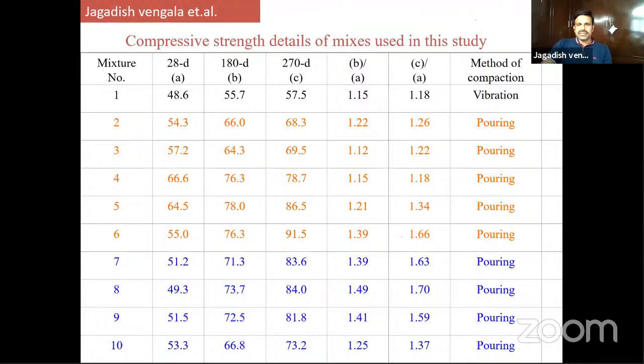So the interesting work here is we used fly ash and we tested, out of curiosity, the performance of SCC at 180 days and 270 days. At 28 days we got around 50 MPa, but at 270 days we almost got 90 MPa strength. Almost 70% more strength when compared with the 28 days strength. So all the cubes, whatever we made, we just poured the SCC into the molds.